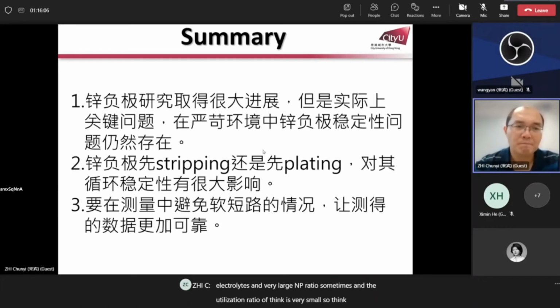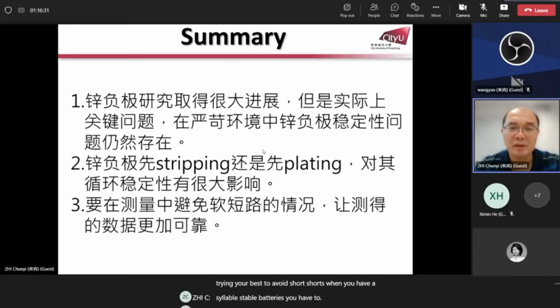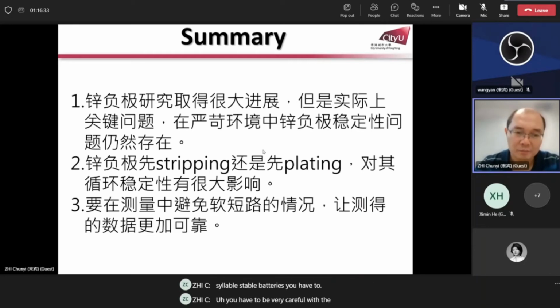So for zinc anode, if you do initial stripping or initial plating, that matters. That will affect the evolution of morphology in the following cycles, very much. And also, when you do the measurement for symmetrical batteries, try your best to avoid soft shorts. When you have super stable batteries, you have to be very careful with the soft shorts issue.